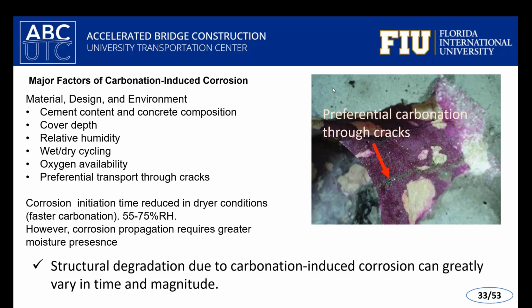So this is where it becomes kind of complicated for the carbonation process, because in order for the gases to penetrate into the concrete, it really prefers drier environments. So the drier the concrete is and the drier the environment you have, the more likely chance you have for that CO2 or even oxygen to penetrate through the concrete to get to the steel surface to promote these reactions. But if you don't have enough moisture, you cannot couple the anodic and cathodic reaction system. So really it's these wetting and drying cycles that are aggressors in terms of how corrosion can develop at rates that can be detrimental to the service life of our structures.